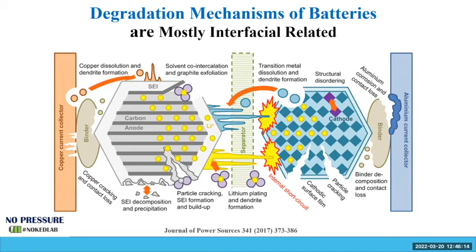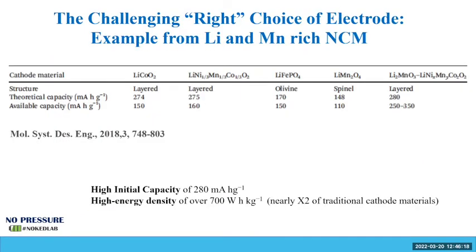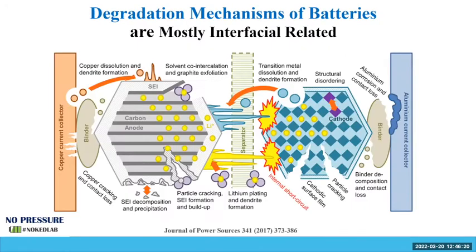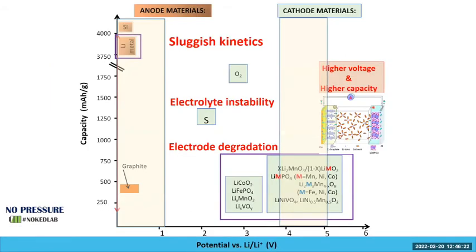One example of how we really can improve the capacity or the energy density is silicon, because when you react silicon with lithium, there is an alloying reaction. When you take graphite, it is interstitial diffusion of the lithium into the graphite. You maintain the gap.